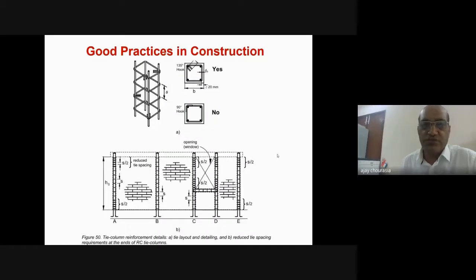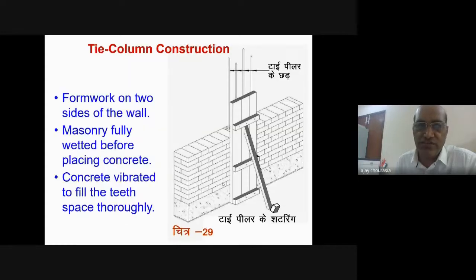These can also be provided if it is not possible to bend the bar adequately into the other perpendicular wall. As regards the spacing of the lateral ties, as I mentioned earlier, at the end regions, 500 mm above and below the slab or floor level should be confined. That is, maximum spacing should be limited to 100 mm, and in the middle half it could be 200 mm. At the overlap portion, wherever longitudinal lapping is happening, the spacing should be limited to 150 mm, along with 135 degree hooks having a leg length of 10D.